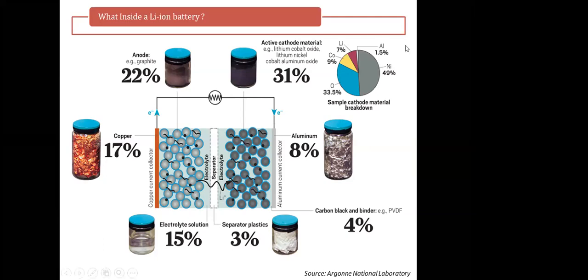Now the most important point: when we talk about the lithium ion battery in India, people basically tell us that in India we don't have lithium, so why should we opt for lithium-ion batteries. But here you can see NCA-based chemistry has lithium percentage of only 7%. If you go to LFP and NCM, it varies from 3 to 6%. So the percentage of lithium is very small. It is not lithium dominated. Mostly people have a little confusion or misconception that we don't have lithium, so we should not go for lithium. Now, a lot of lithium batteries are getting imported. If we have proper recycling policies, that lithium can be reused and made available for producing more lithium-ion batteries in India in coming times.